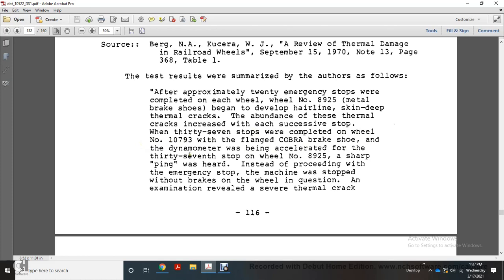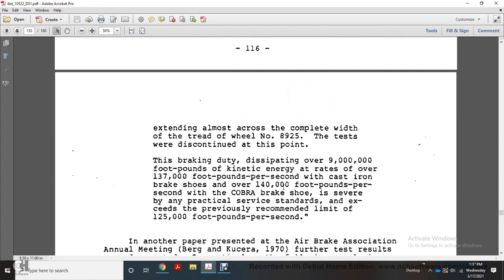The dynamometer was being accelerated for the 37th stop on wheel number 8925 when a sharp ping was heard, instead of proceeding with the emergency stop. The machine was stopped without brakes on the wheel in question, and an examination revealed a severe thermal crack extending almost across the complete width of the tread of the wheel. The test on number 8925 was discontinued at this point.